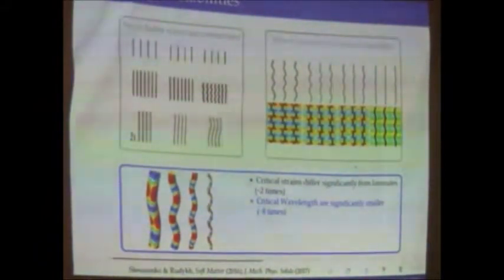I'm just summarizing this: with the instability we can obtain these switchable wavy microstructures, and can even tune them more by introducing rate-dependent behavior. There are quite significant differences if you try to predict the behavior of 3D fiber composites by the analysis of 2D layers, so you can overestimate some important things. And I don't need another half an hour. And I apologize again.